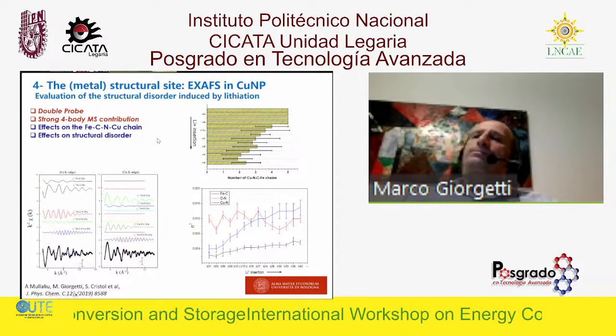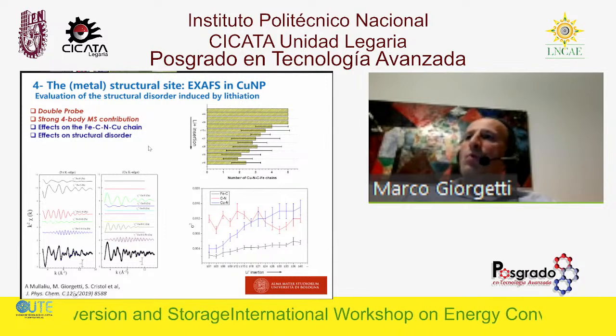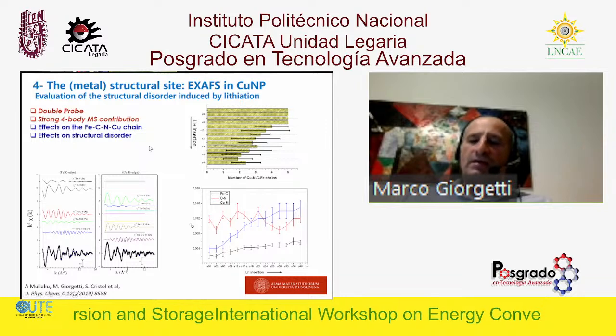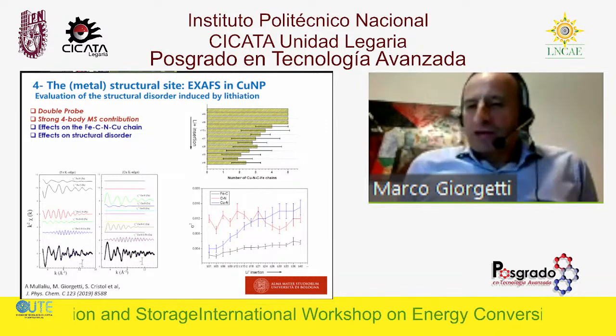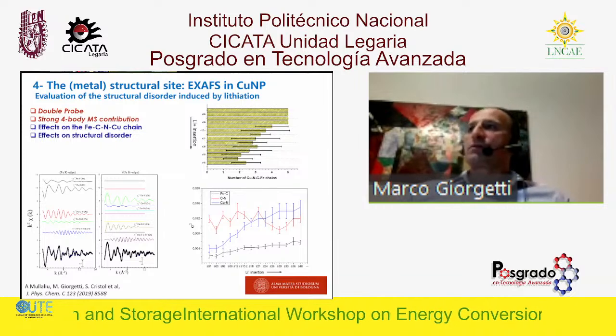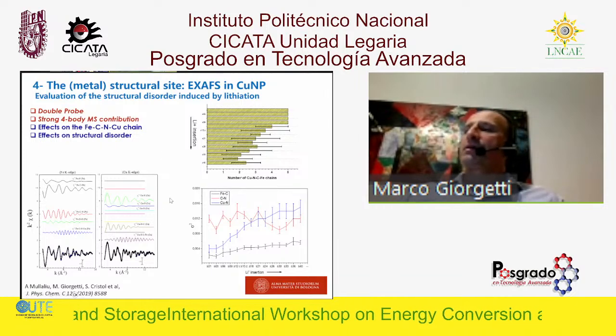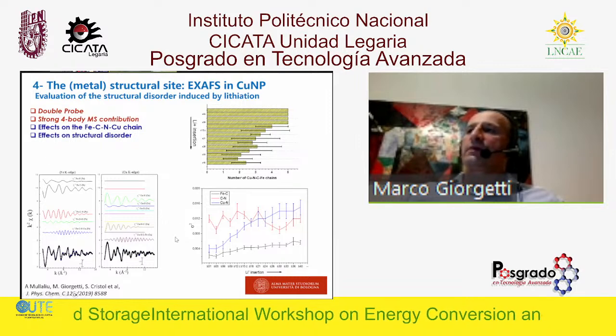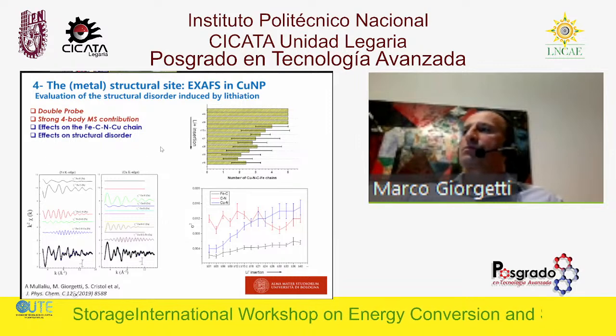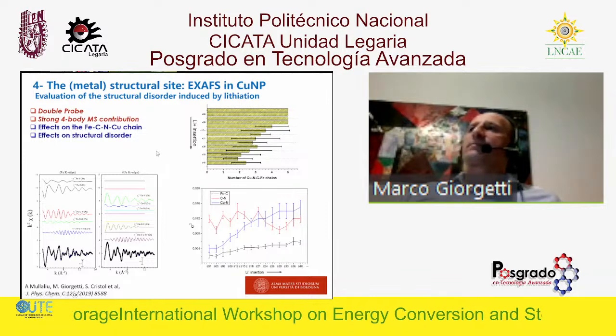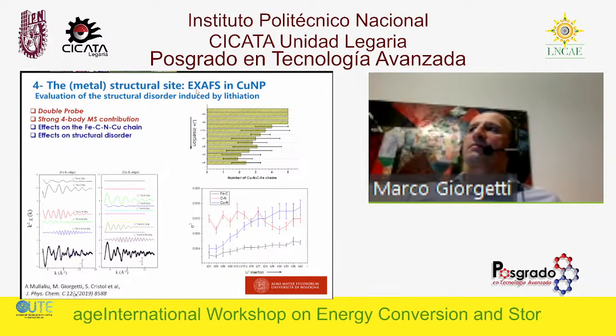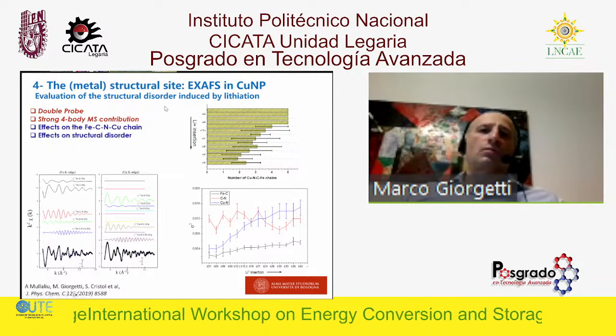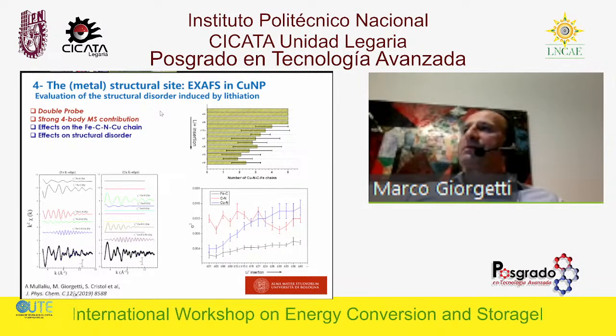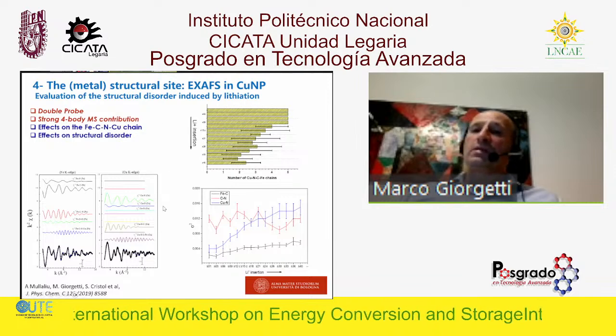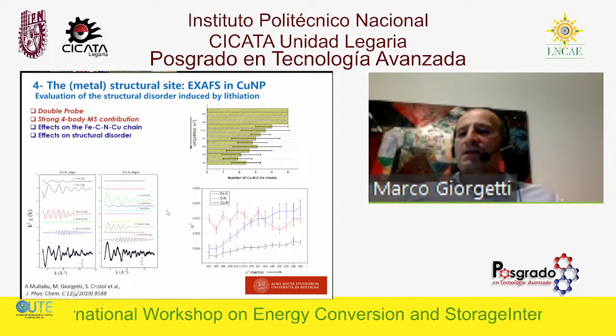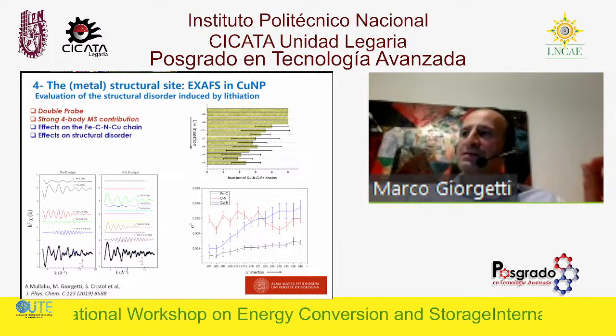About now the EXAFS, and why we want to investigate not only the XANES portion, but also the EXAFS portion. We can see from this graph, I tried just to summarize. There's a lot of maybe incomprehensible things, but just to focus on two things. The one is that it also allows the evaluation of the structural disorder induced by lithiation. This is something that you can do with the EXAFS Debye-Waller factor. This is kind of similar to what we have in XRD, but not exactly the same.